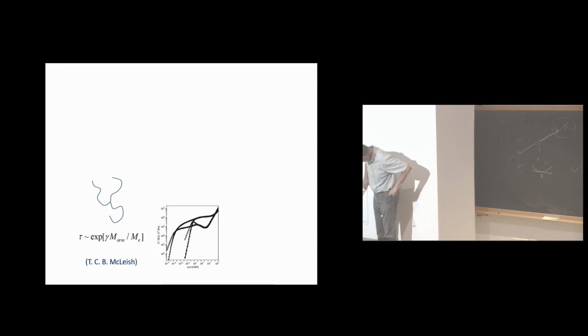And so this is from the Rubinstein-Colby book, but it's data by Lynden Archer. And so we can easily now see that this data here refers to the linear polymer, say the molecular weight of the arm, with a clear plateau and the terminal crossover. This is moduli versus frequency. Shifted frequency, you may remember it was discussed recently. But then the arm, because of its effort to do this, which obviously is entropically unfavorable, it takes many trials to do it. And so then eventually it does it, but look, the G double prime is extremely broad. So this is known.